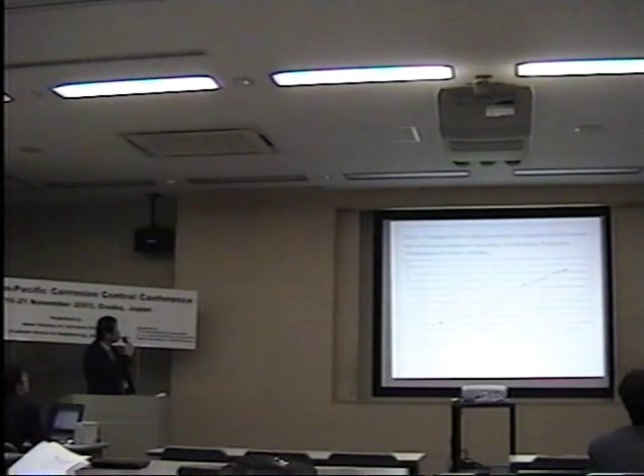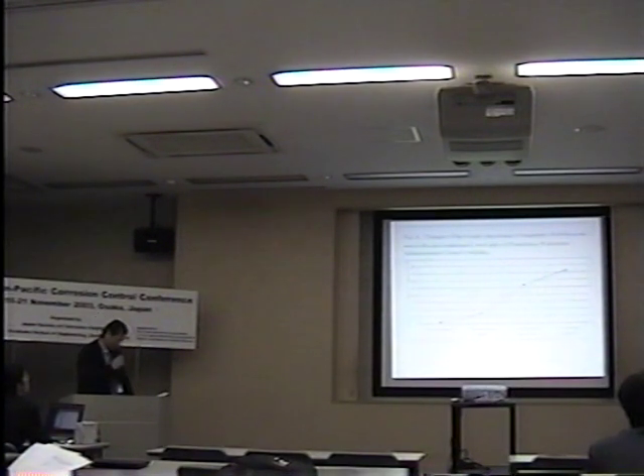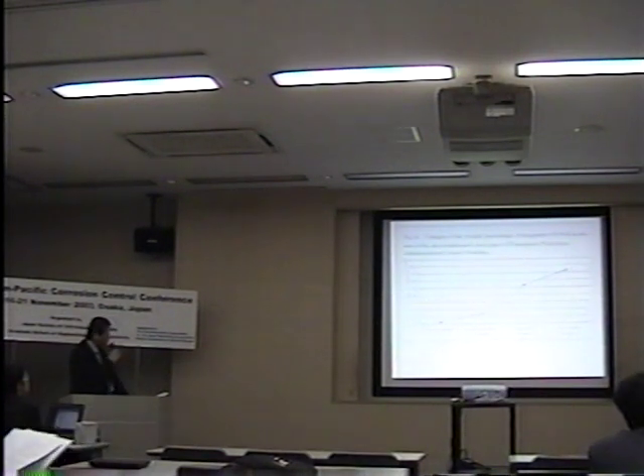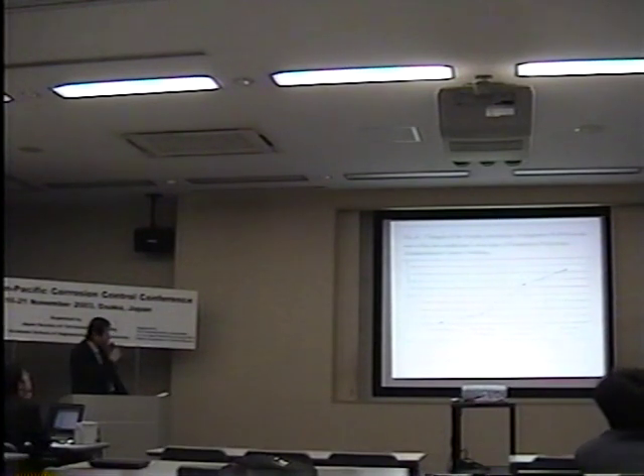Figure 4 shows the change of the weight percentage of magnetite Fe3O4 in the steel pipe of the air conditioner of Foundation Wakabadai Administration Center's buildings. As you see, weight percent of magnetite Fe3O4 was increased from 2.2% to 72.9% after 12 months of installation of NMR equipment. It is clear the NMR phenomenon reduced corrosion FeOH to magnetite Fe3O4.